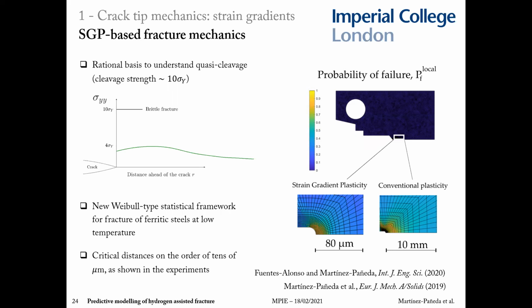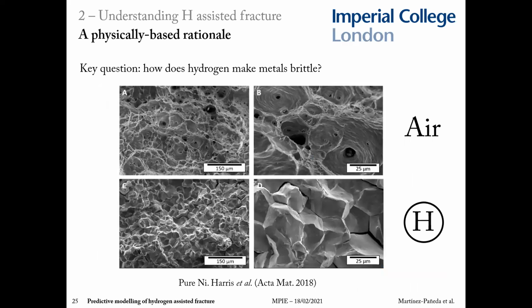Because the theoretical lattice strength or the cleavage strength are of the order of 10 times the yield stress. So you need higher stresses coming from somewhere in order to rationalize these brittle processes from a mechanistic point of view. For example, we had a lot of fun with this approach, and we looked at fracture of bimaterial interfaces, where you can also model dislocation pileup, and also developed statistical frameworks for low temperature cleavage of ferritic materials. But let's go back to the hydrogen problem.